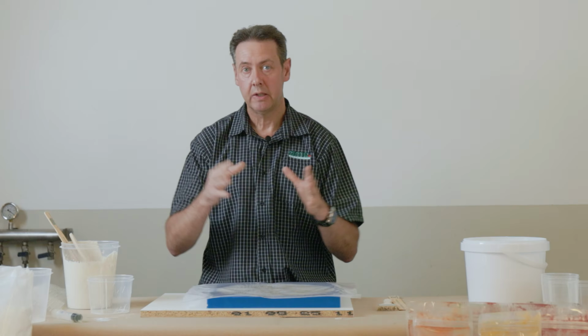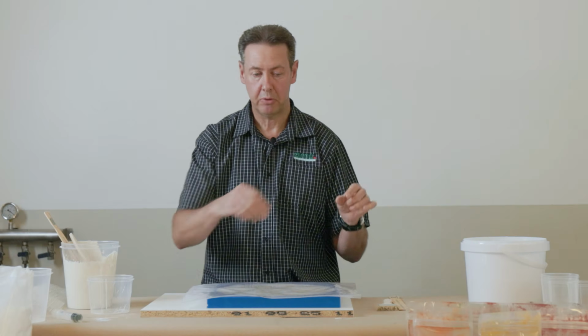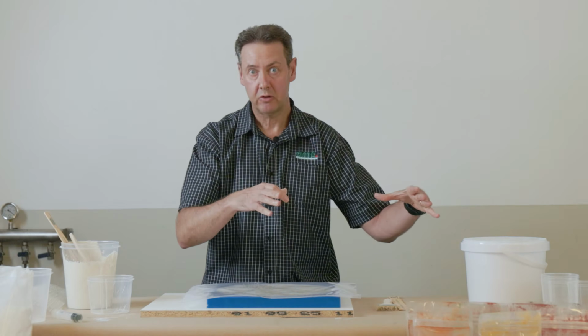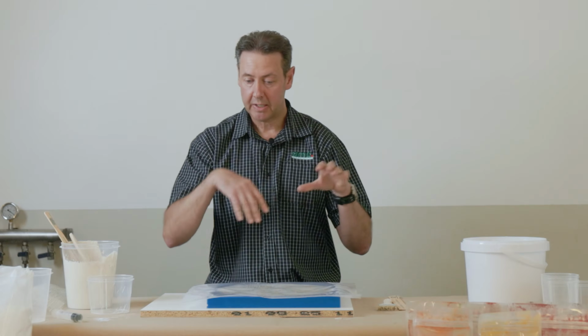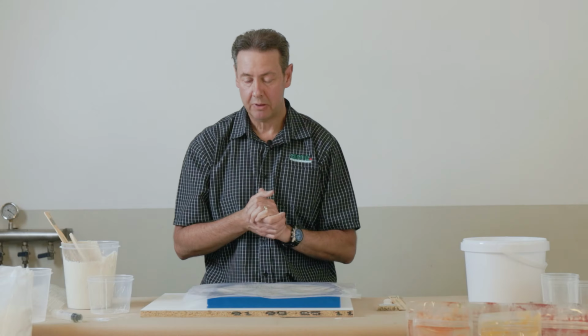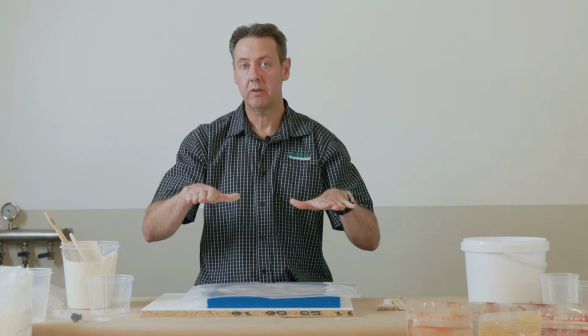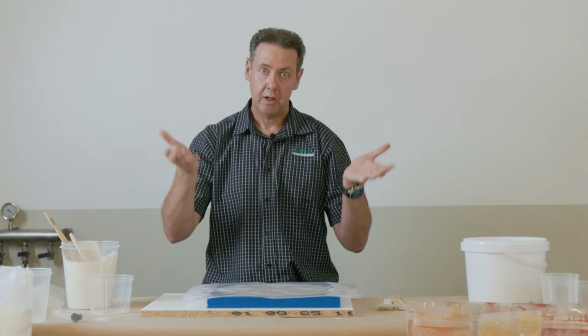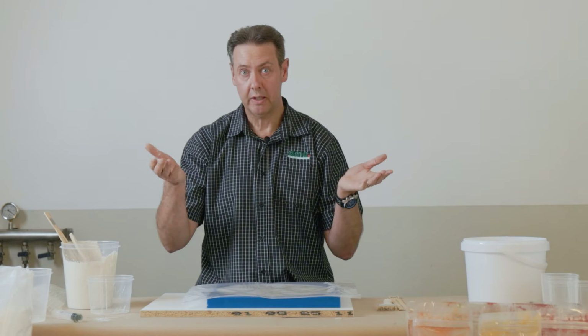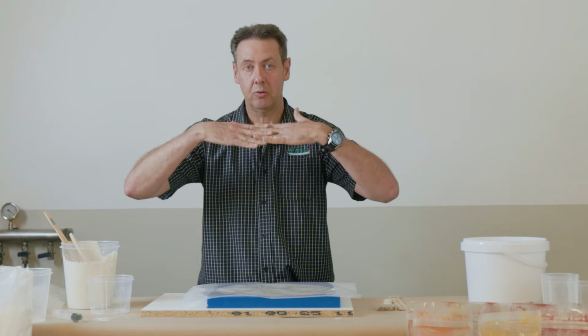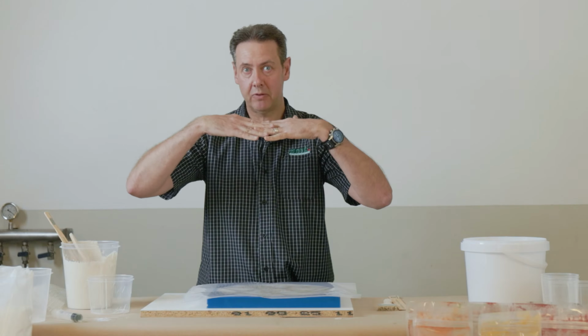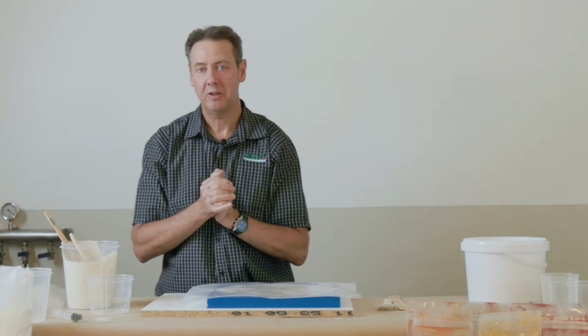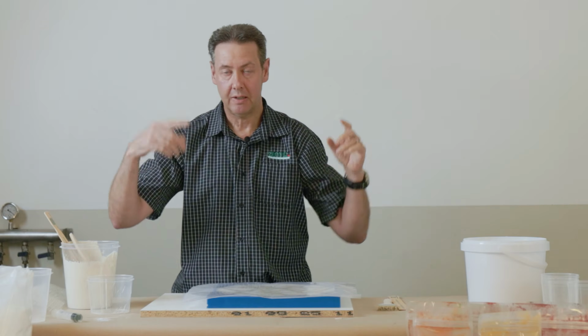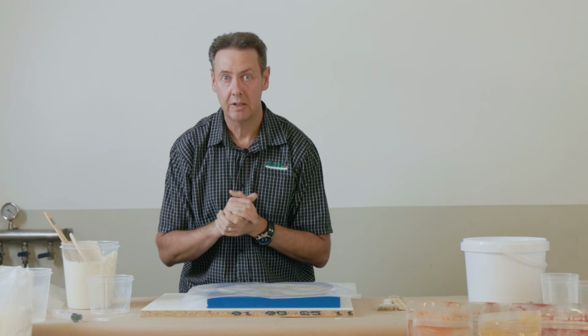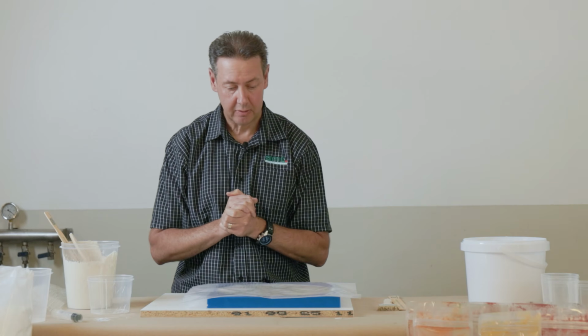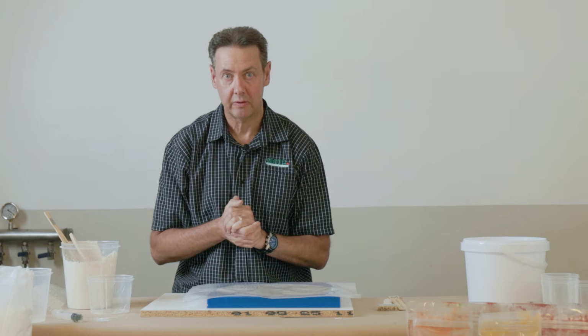And very important, when we air dry it, we want the air to be exposed to all sides of this piece. So we can put a couple of strips of wood down and then put the laminate on top of those strips of wood. And we just want to be able to air dry around the whole piece. If we've done, let's say, a tabletop, might be a square meter tabletop, and we put that down flat onto the ground to air dry, what will happen is we have the top drying out a little bit quicker, and the bottom actually staying damp, and it'll cause the panel to warp. That's called a smiley or a frowny, but it's normally a frowny, as we don't want that to happen. So very importantly, as I mentioned, put some strips of wood down and let that piece hydrate and dry out nicely on both sides. And that is the glass fiber reinforced concrete process.